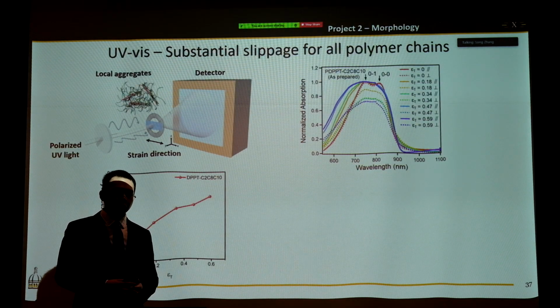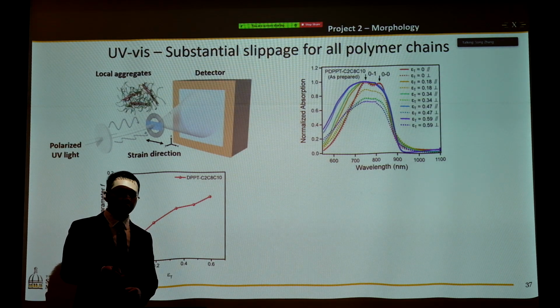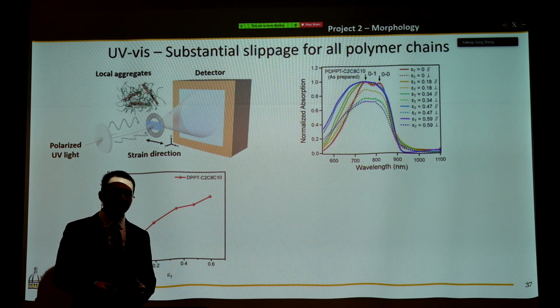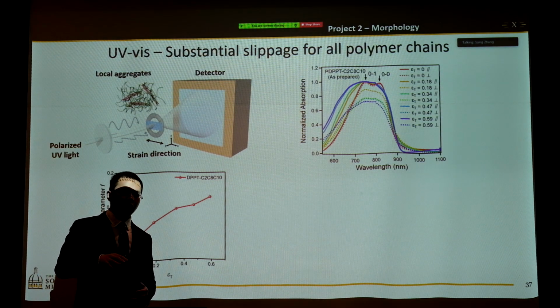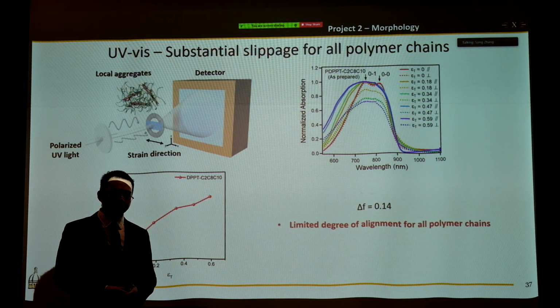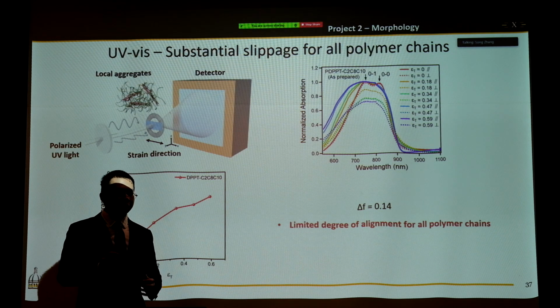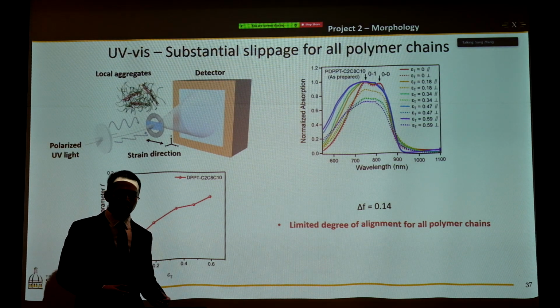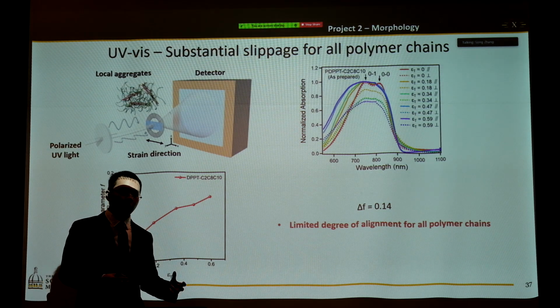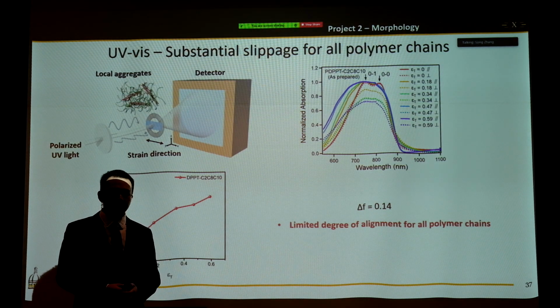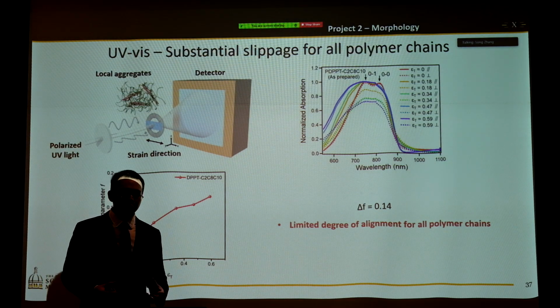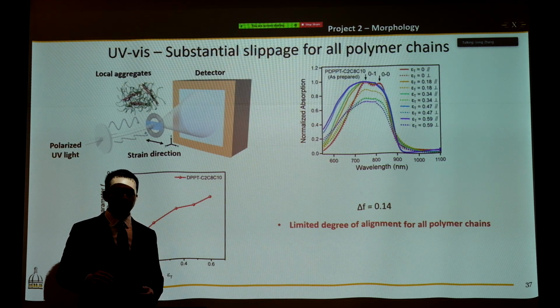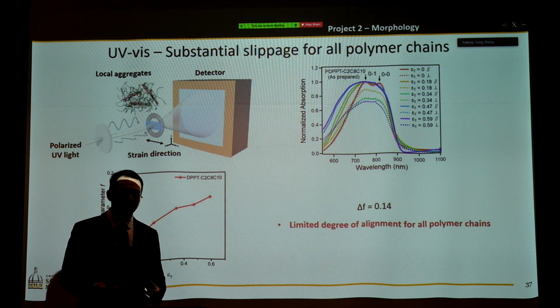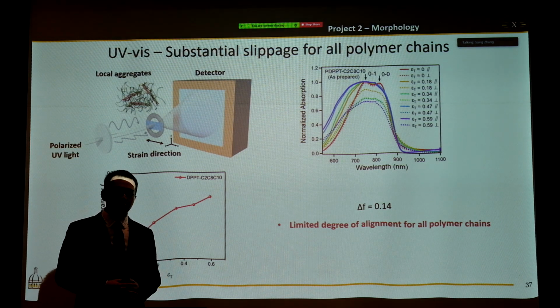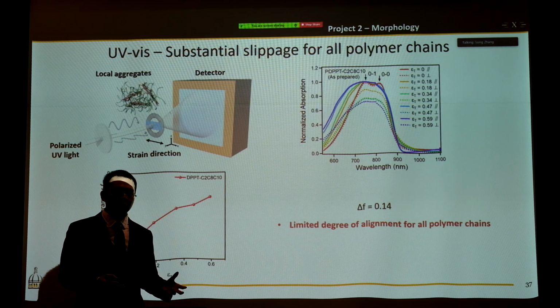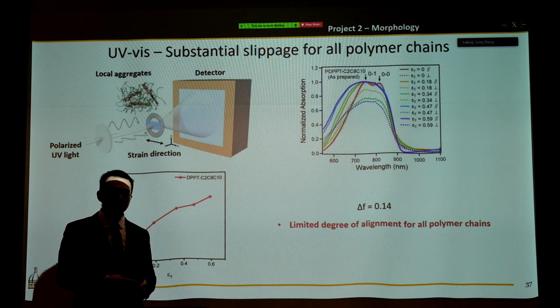Now it comes to the polarized UV-Vis. From the absorption peak, we were able to measure the dichroic ratio for parallel versus perpendicular direction, and the delta F value is calculated to be around 0.14. And this number is significantly smaller than all the numbers we've reported previously. So we saw the backbone alignment in the crystallite is equal to 0.423, and this is equal to 0.14. So it suggested to us that the slippage of amorphous chains is more significant than the slippage of backbone. And that can be understood because in the crystalline domain, you still have this pi-pi interaction as the impedance force.